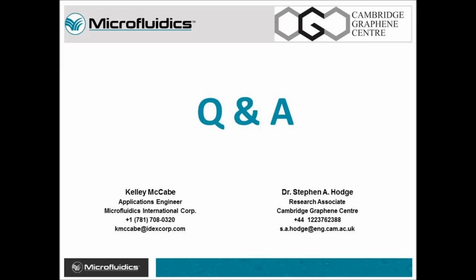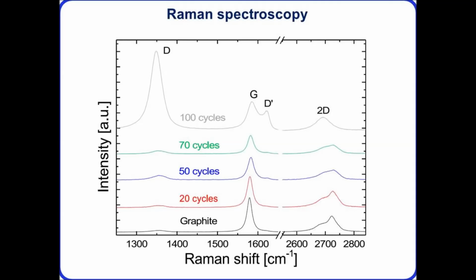That's great. And in fact, we know we are over-processing the material. After around 70 process cycles, we start to actually degrade the graphene that we're producing. I can show one slide on this, if I'm still sharing my screen. Yep. So if we look at the Raman spectroscopy, which is a very good method for graphene characterization, we have the appearance of this D peak, which is a defect-induced mode, and that becomes very apparent after 70 cycles of processing.